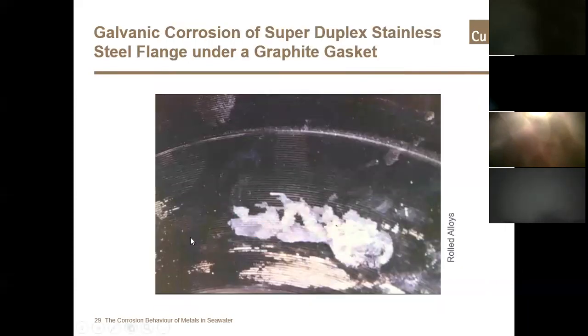And another example would be the galvanic corrosion of a duplex stainless, where it was used for a stainless steel flange. A graphite gasket was placed in between the flange, and as you can see from the white area, galvanic corrosion has occurred, and there's quite a significant metal loss. So even something that is apparently quite noble in a duplex stainless, if it was coupled with the far more noble graphite gasket, then we would get issues.